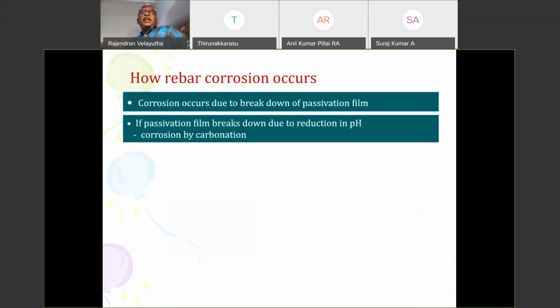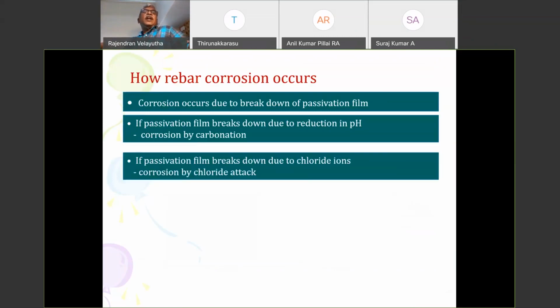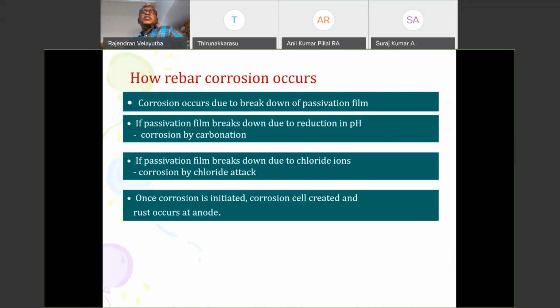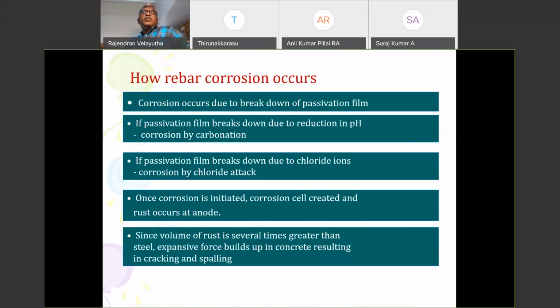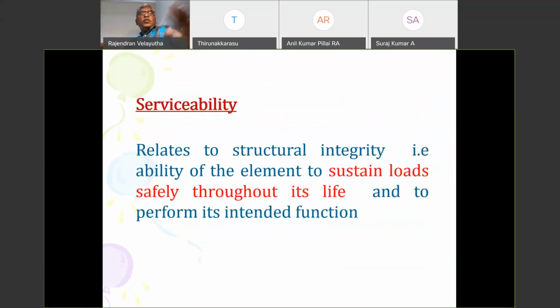So the passivation layer is broken because of carbonation, which reduces the pH value, and chloride attack also breaks the passivation layer over the rebar. Once corrosion is initiated, rust occurs at the anode. Since the volume of the rust is several times greater than that of the steel, obviously expansive forces are active, and this results in cracking, which is a known fact to all of us. I'm just giving you a recap of it.